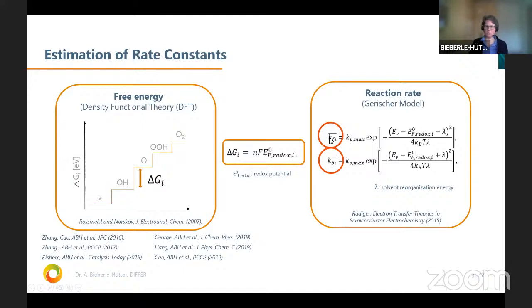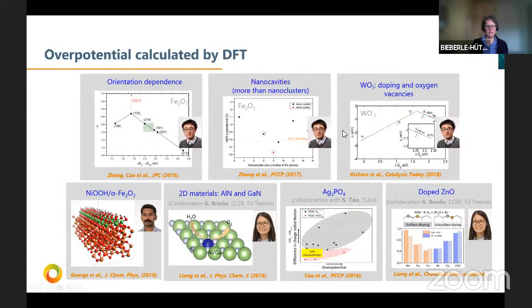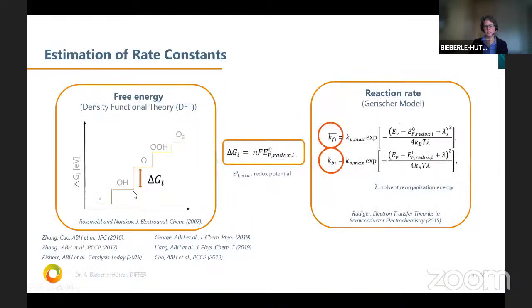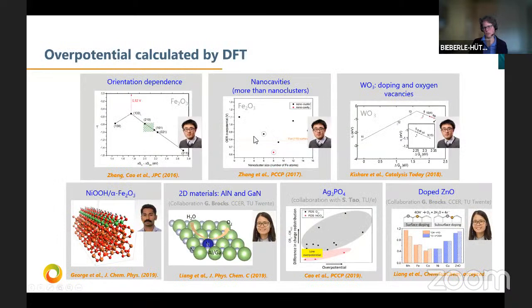I always say estimate because DFT is under very ideal conditions. So when we compare this to our experiments, it's an estimation. It's a starting value actually. But like this, we can estimate these rate constants. I show in this slide that we do this DFT to estimate some starting values. This is one motivation, but we also did this DFT to try to find out what impacts the overpotential, because the largest step here is the overpotential, and we would like to figure out the reason that the overpotential is different.